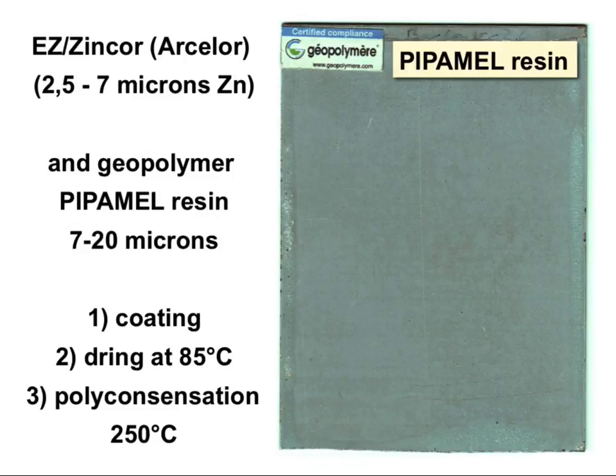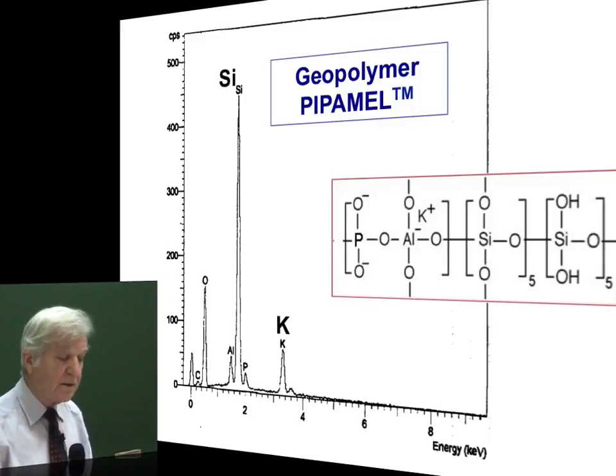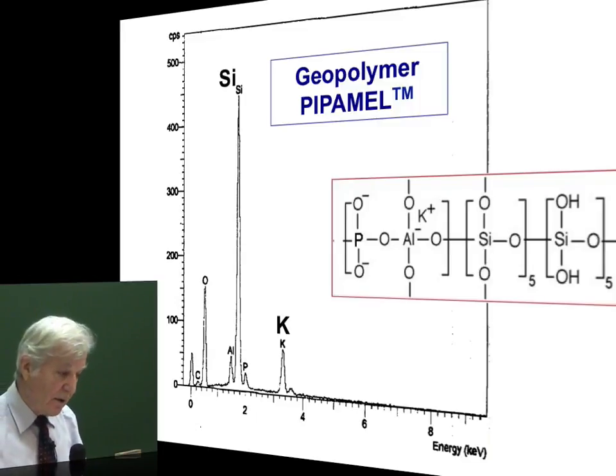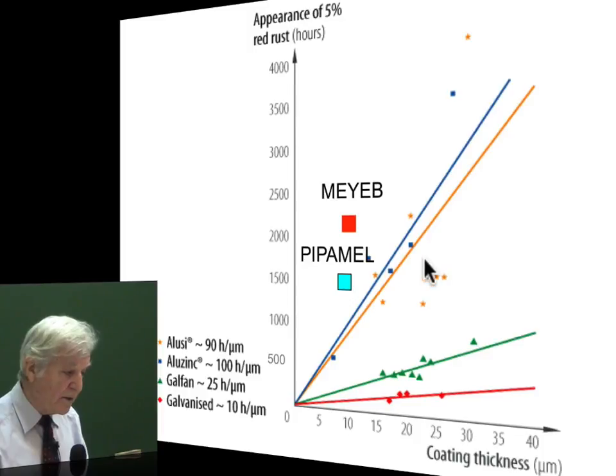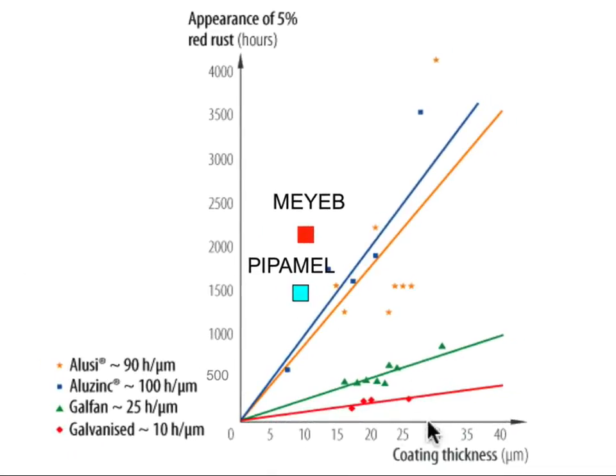Very easy to polycondense, drying at 85 degrees C, polycondensation at 250 degrees C. And we achieve a corrosion strong, resistant material. The resin looks very complicated. It is a phosphate aluminum silicate based system that in comparison, these are the 7 microns sheet that we applied on our plates.